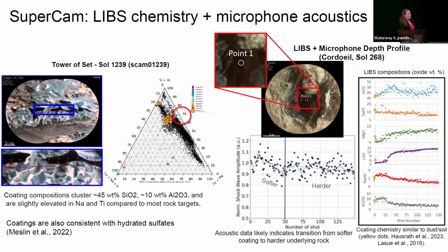Looking at some of the acoustics plus LIBS chemistry data over here, this is a target called Cordoeil. And in the acoustics data, LIBS is a technique that will produce a little shock wave whenever each laser strikes the surface. And so you can use that information to get a sense of the material properties, in this case, the relative hardness between the coating and the substrate. And so you can see the change in slope at around shot 50 as we penetrate into the rock. So you can see we're kind of delving into a softer material and then hitting a harder material.